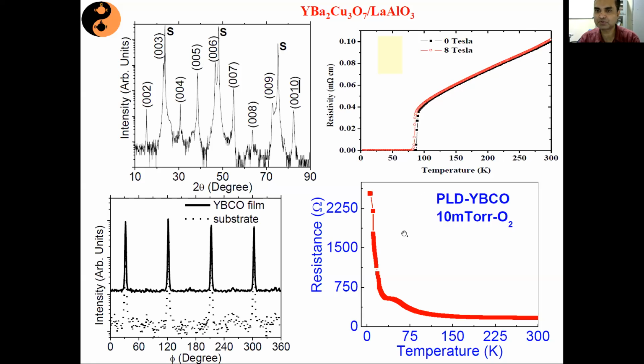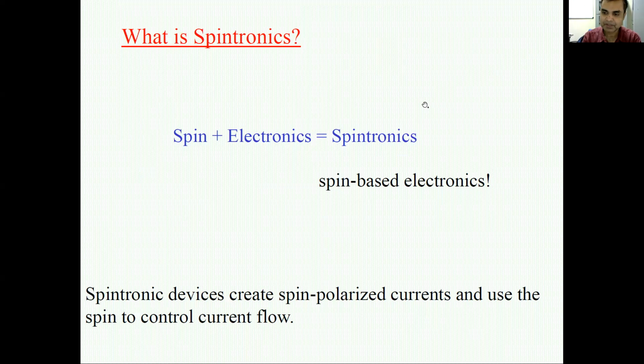Look at this YBCO, which was optimally grown, with Tc at 90 Kelvin. There is a sharp drop in resistivity at 90 Kelvin. But when you grow its film at say 10 millitorr of oxygen partial pressure, it loses all its superconducting property, and its properties are gone. Now, this was all about the techniques to grow thin films.